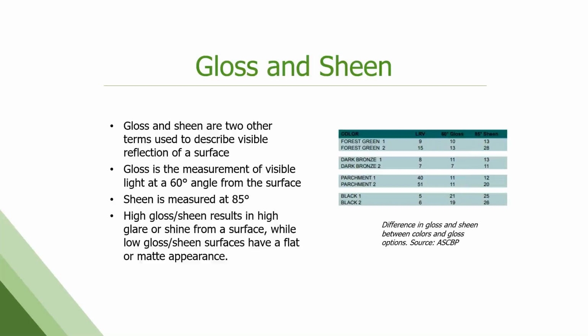So at this point in time, most of the standard paint systems for exterior building products are probably in the 10 to 20 range for gloss and sheen. We've seen that number come down over the years for a couple of reasons. One, as it gets used more in residential, your neighbors don't want to be blinded by your roof, so that's a problem. And it's an issue around airports and military bases too for aircraft. They don't want to be blinded by a building on the ground they're trying to operate near. But if you get the gloss and sheen down to 8 or less, which is quite low, you get a pretty matte finish with not much light reflectance on it.